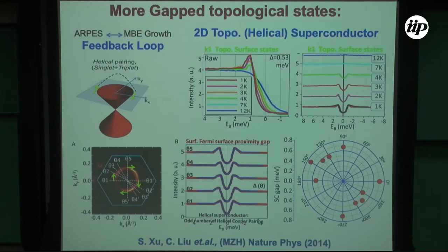Okay? So then, as I showed yesterday, if you are just looking at the topological insulator surface, you'll see a Dirac cone. You have a circular Fermi surface. If you do spin measurement, you'll see spin-momentum locking, this helical locking. So what is new in this experiment is that we want to cool the sample heterostructure below the transition temperature and see whether the Dirac cone is superconducting. In other words, is there Cooper pairing going on in the Dirac helical state? ARPES is, again, a fantastic tool for that because we can image the k-space location.